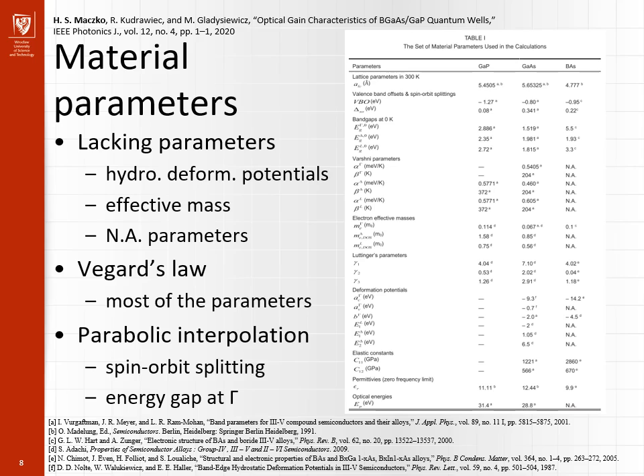In case of hydrostatic deformation potentials of the bands at gamma point, only the deformation potential of the direct gap was available. It is put as the deformation potential of the conduction band only in the calculations. Effective mass of electrons in the gamma valley is estimated by fitting parabola to band structures found in literature. Some parameters, however, remained not available. We approximated them by proper values of gallium arsenide, the second binary compound of boron-gallium arsenide alloys.